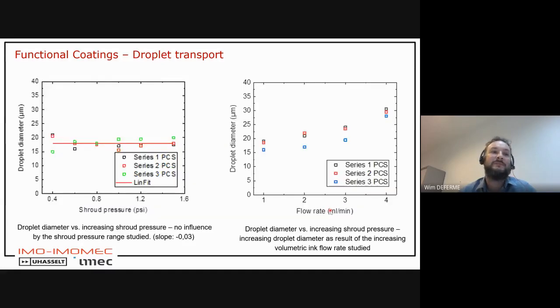And a final one was the influence of the shroud pressure and the flow rate on the droplet diameter. So we had the droplet speed on the one side where we saw nice correlations, but you see that the shroud pressure is not influencing the droplet diameter, which is also something we expect, or we hope anyway, because of course the carrier gas should not influence your droplet diameter. However, if you look at the flow rate, you see that the higher the flow rate becomes, the bigger the diameter becomes. And that probably has to do with the fact that you have more material there, and more material means that the droplets are closer to each other, and you have the chance that some droplets will merge and form bigger droplets. So this is a relationship between the droplet diameter and the flow rate.